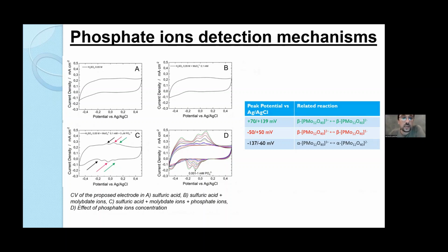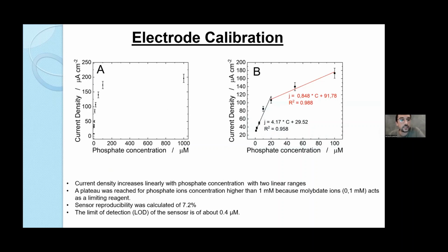So we find out that the current density increased linearly with phosphate concentration in two linear ranges, from 0 to 20 micromolar and from 20 to 100 micromolar. A plateau was reached for phosphate ion concentrations higher than 1 millimolar because the molybdate ion concentration is fixed to be 0.1 millimolar. Thus, at higher concentrations of phosphate ions, molybdate starts to act as a limiting reagent.